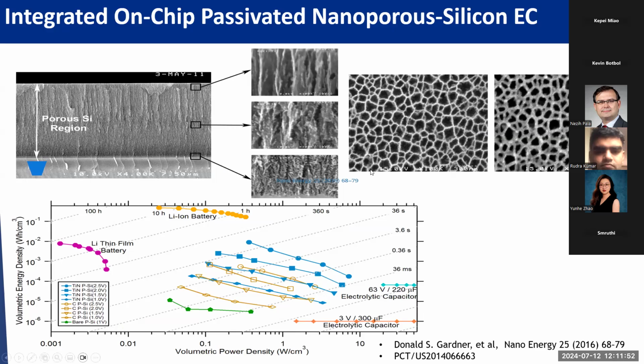So it's very uniform. And we can coat this polysilicon using ALD, coated with either carbon or titanium nitride, aluminum nitride. ALD is another powerful approach, can do the uniform coating at a very low pressure. So we can coat this polysilicon. The reason why we coat it is freshly created polysilicon is not that stable. So the surface is very easy to be oxidized. So when you have a coating, you can maintain the stable surface and high surface area.